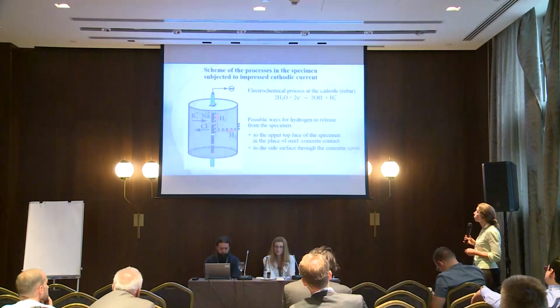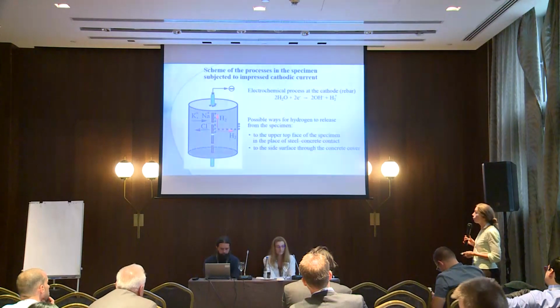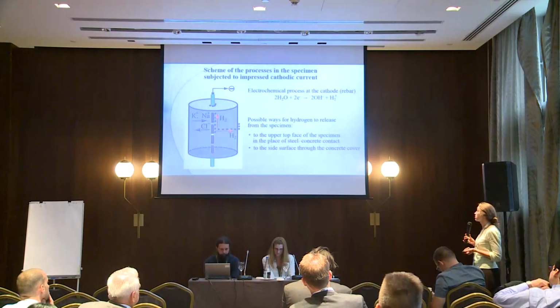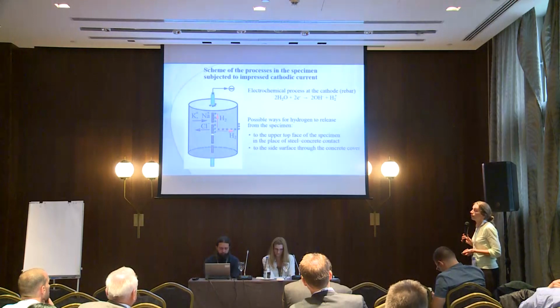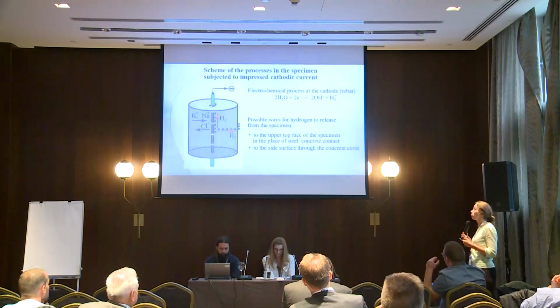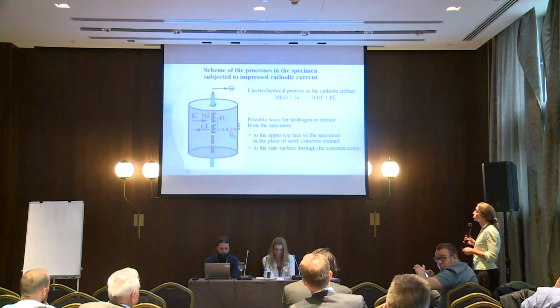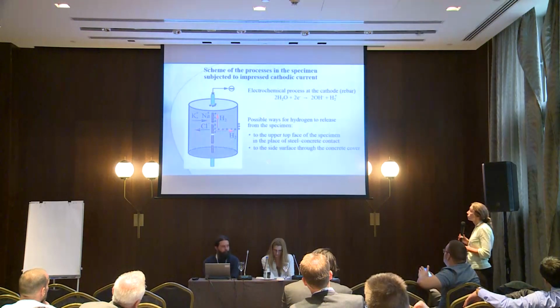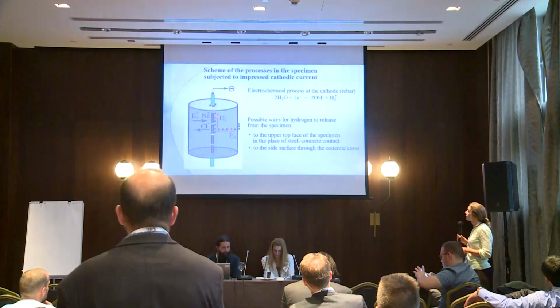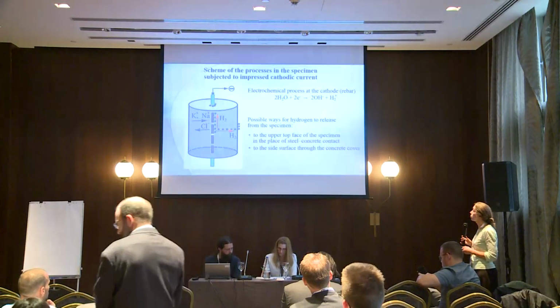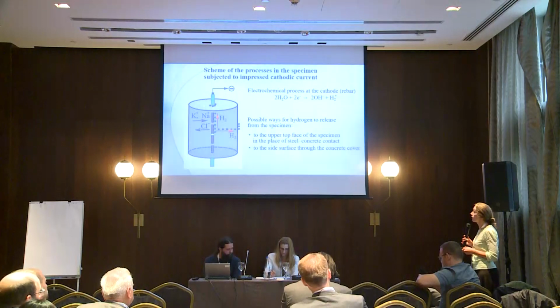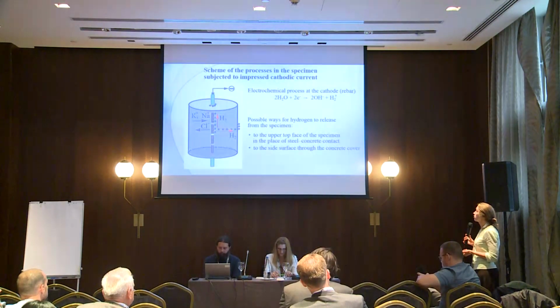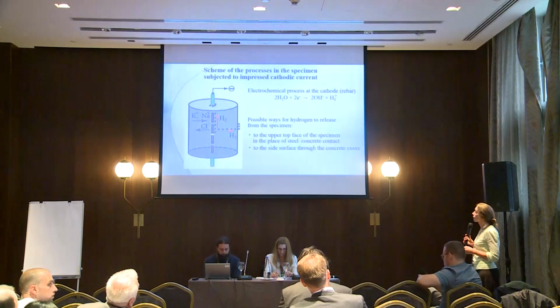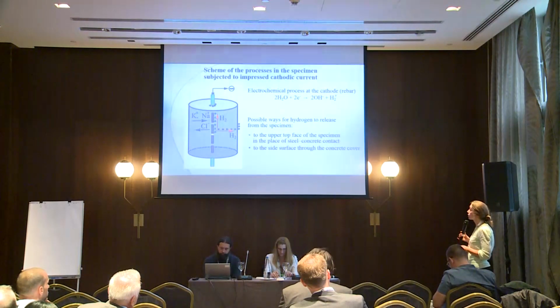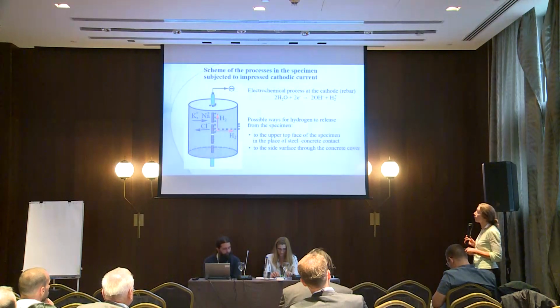And the question is whether its movement is equilibrium or is accompanied by creation of some internal stresses in the concrete matrix, which could later influence the structural integrity of this composite. When hydrogen moves upwards, it could destroy partitions in the concrete near the reinforcement, and also it is a way for weakening of bond strength in reinforced concrete. So under cathodic polarization, adhesion disturbance in reinforced concrete specimens could be caused not only by electromigration, but also as a result of hydrogen evolution at the steel surface.